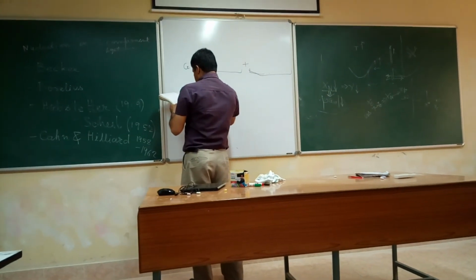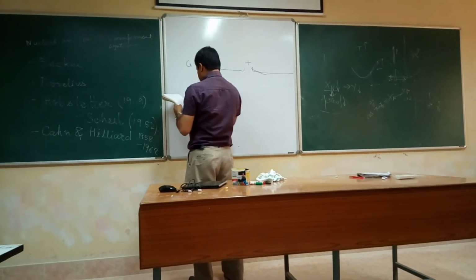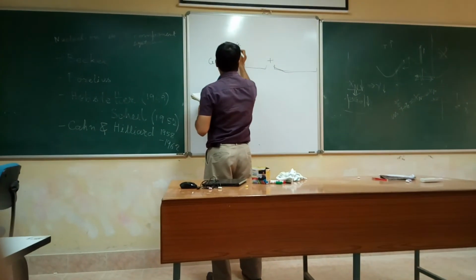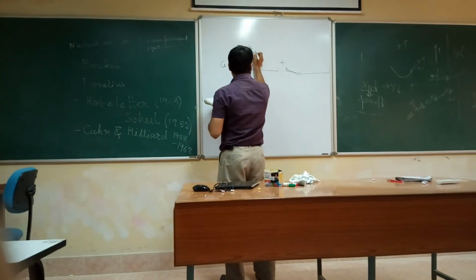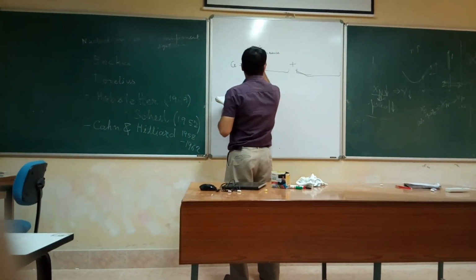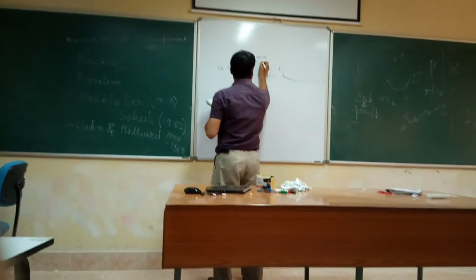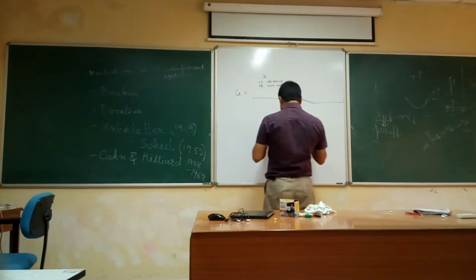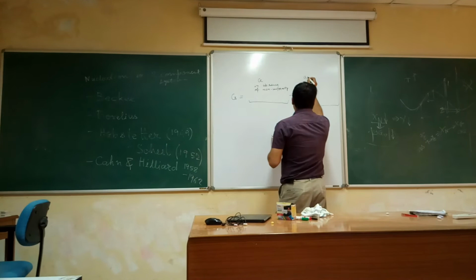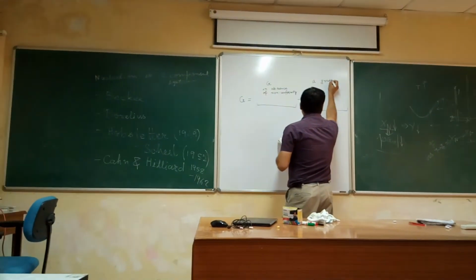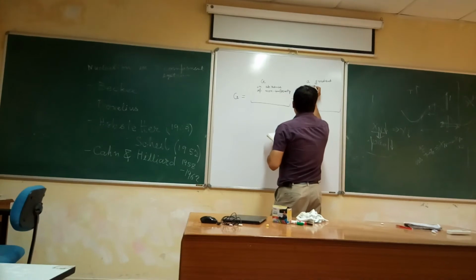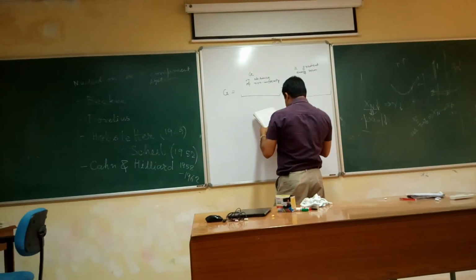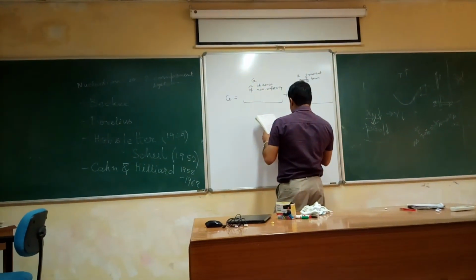One is the free energy that the volume has in the absence of non-uniformity. And another is a gradient energy term, which is a function of local variation in composition.